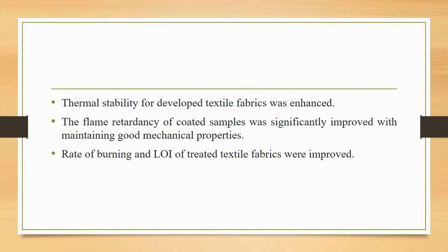So lastly, in conclusion to our report, furniture textile fabrics were coated with a novel thin coating layer. The mass ratio of ammonium phosphate was optimized. Titanium dioxide nanoparticles of an average size of 20 nanometer were dispersed in the coating layer and their effect was investigated. Thermal stability for developed textile fabrics was enhanced. The flame retardancy of coated samples was significantly improved while maintaining good mechanical properties.